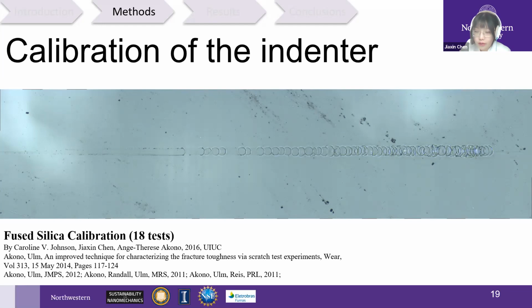Actually, we have to make a lot of assumptions for that, because recently we applied it on brittle materials like cement and also polymers. Even though gel is a soft material, here we use gel crystals instead of the gel itself. And when we apply scratch testing on soft materials, I'm not sure if I'm correct, but I think surface friction dominates the behavior instead of fracture. So if we want to apply it to softer materials, we may need a lot of effort to figure out how to set up the experiment. That is my understanding.